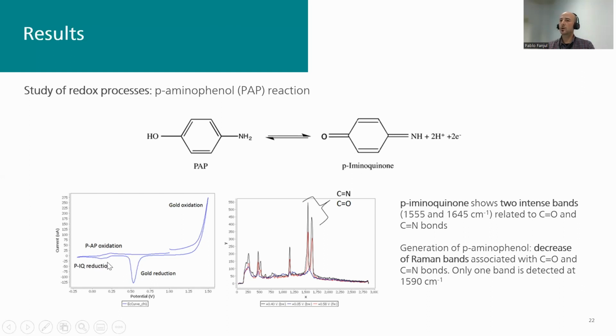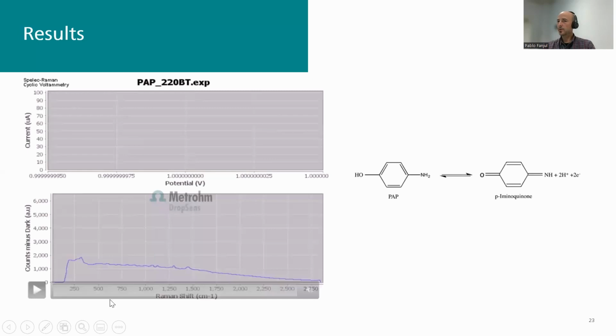reaction. So here we have this reversible process that corresponds to the reduction of the quinonimine to paraminophenol and to the oxidation of aminophenol to iminoquinone. So we carry out the electrochemical process here. We will see how we oxidize the gold electrode, how we reduce it. And once we have done this electrochemical process and we have the SERS active substrate, is when we will get the spectra of the aminophenol, and we can see the change in the spectra, and we can get as well the spectra of the iminoquinone when it has been reduced.